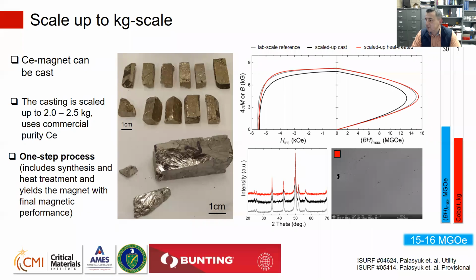What is the energy product for cast bulk versus wax aligned material? I think the energy product for cast bulk would be 10 MGOe, 10, 11. But it depends how you measure, and you could be lucky and measure it along the grain which is aligned, and then there will not be a difference because grains of this material are large.